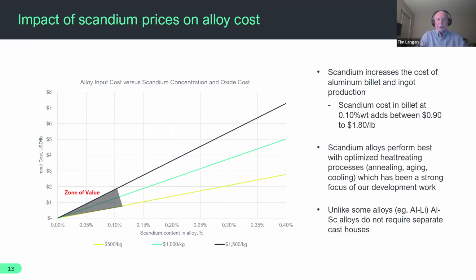Historically, alloys had about 0.25 weight percent scandium. We're pushing that down as close to 0.1. So the important takeaway is if we have about 0.1 weight percent scandium with an oxide price of about $1,000, we add about $1.50 a pound to the billet cost. The current LME price is about $1.30, $1.20 a pound. So essentially we're doubling the price of the alloy billet.